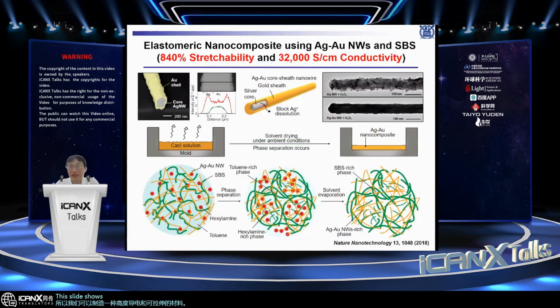This slide shows an example. In this case, we used thermoplastic elastomer, SBS, and SBS was mixed with metal nanowire, a silver core and gold shell, core-shell type nanowire. The reason why we used the core-shell type nanowire is because, first of all, silver provides the best conductivity among all metals. So to maximize the electrical performance of the stretchable conductor, we had better use a silver-based metal nanomaterial as a conducting filler because silver has very high conductivity. But the problem is that silver can be easily oxidized, as shown in this image, under biofluid, under sweat, under blood.